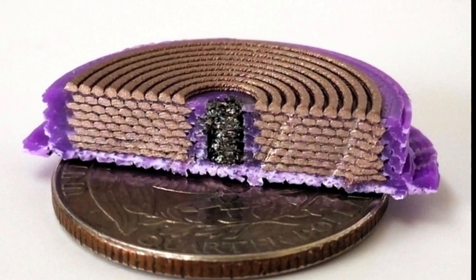The team selected a printer with 4 nozzles, one dedicated to each material to prevent cross-contamination. They needed 4 extruders because they tried 2 soft magnetic materials, one based on a biodegradable thermoplastic and the other based on nylon. They retrofitted the printers so one nozzle could extrude pellets rather than filament. The soft magnetic nylon, which is made from a pliable polymer studded with metallic microparticles, is virtually impossible to produce as a filament. Yet, this nylon material offers far better performance than filament-based alternatives.